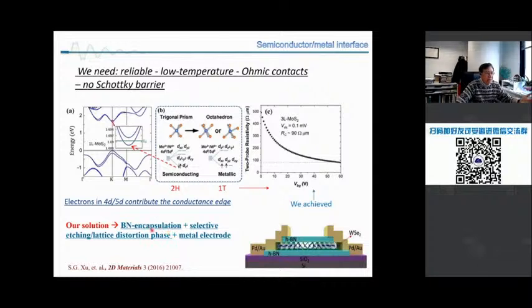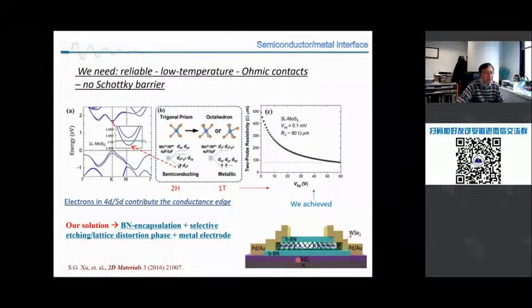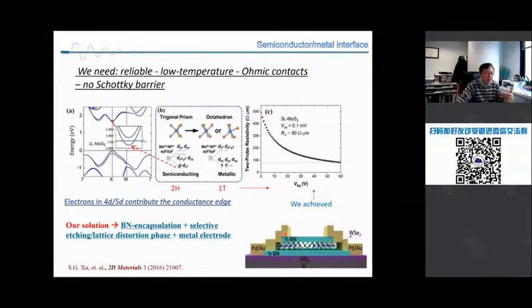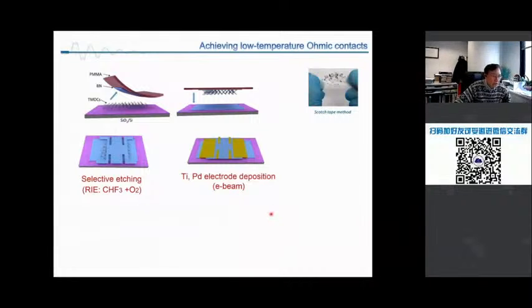Now, first we use an encapsulation structure because boron nitride is clean. If you make a sample directly on silicon dioxide, there's charge impurity scattering. The mobility cannot be high. So boron nitride is ideal. And then we use selective etching to make lattice distortion and deposit the metal electrode. So let me show you the principle.